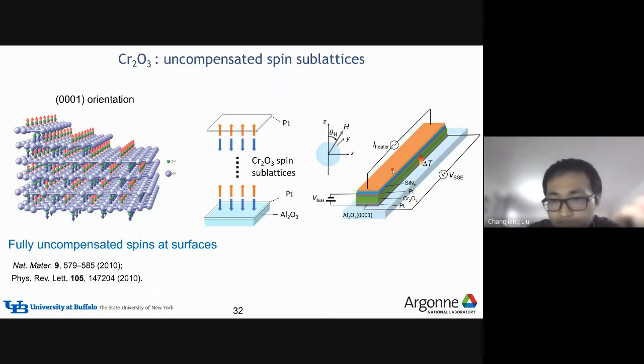So this is the device structure. In the experiment, we grow this chromium oxide on a sapphire substrate, 0001 oriented, and we first grow a platinum layer on top of sapphire, which is used as a spin detector, and then we grow a chromium oxide, and this chromium oxide is sandwiched by another platinum layer, so in both of these cases we can use top and bottom platinum to measure the spin current. We could also use these two electrodes to apply voltage across this interface, across the chromium oxide layer. At the top, we have a heater, as I just described earlier, which can generate a temperature gradient in the vertical direction.